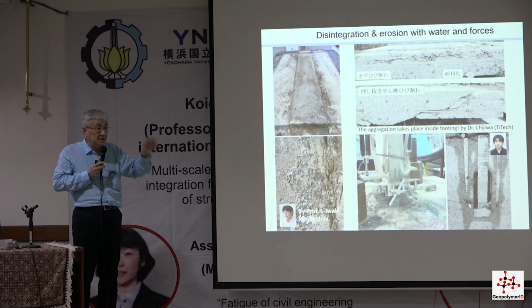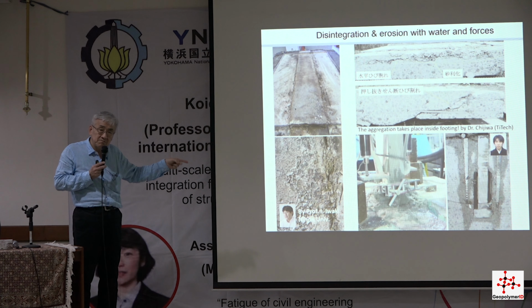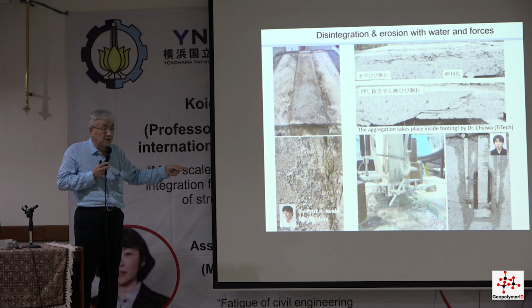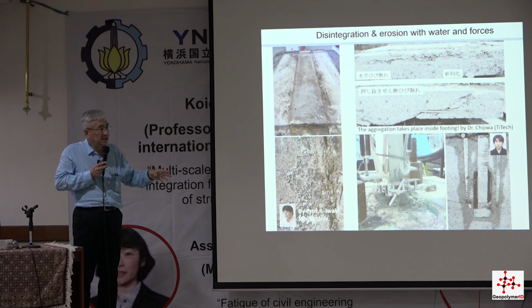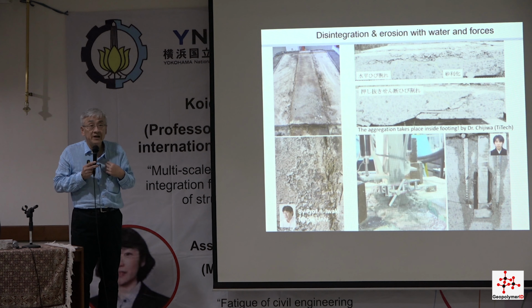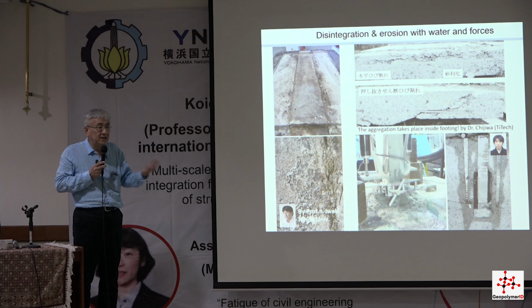But the strength difference between WC 50% and 55% is very small. Not so much, but the performance against the water is quite different. Therefore, WC 50% concrete and WC 55% concrete are different materials. We should consider these different materials. Therefore, I checked design codes all over the world. According to experience, many countries say that for marine concrete structures, always exposed to water, the water to cement ratio should be less than 50%. This is deep experience, maybe.